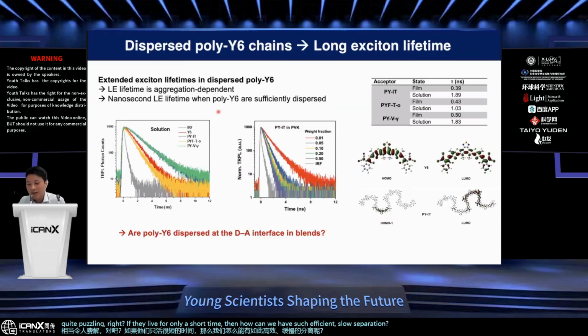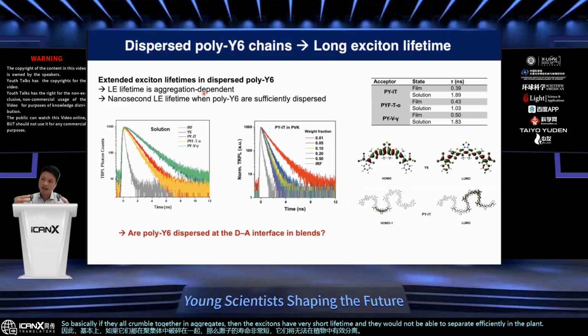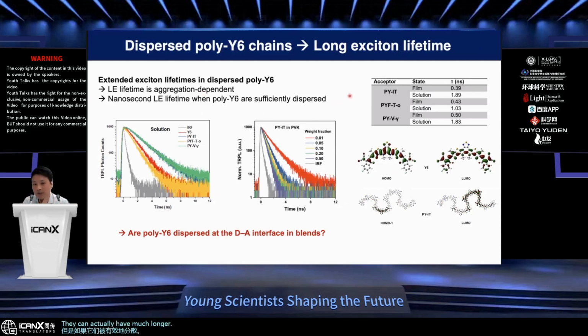So interestingly, what we found was that in the pure film, they do have very short lifetimes. But as we disperse them in a solution, or in an insulating polymer matrix, we find that the lifetime of the exciton is very much aggregation dependent. So basically, if they all crumble together in aggregates, then the excitons have very short lifetimes, and they would not be able to separate efficiently in the blend. But if they are efficiently dispersed, they can actually have much longer lifetimes, which will satisfy the condition for efficient endothermic charge separation. So then that leads us to think,